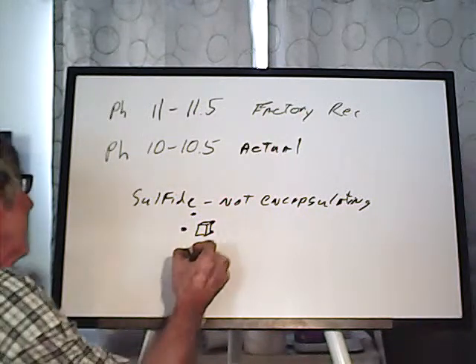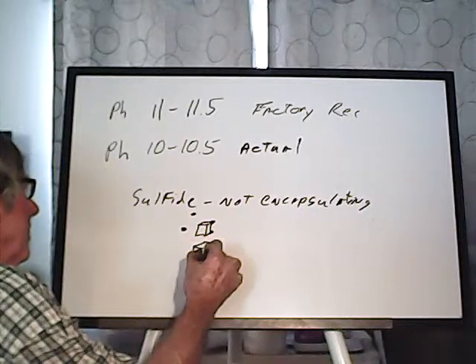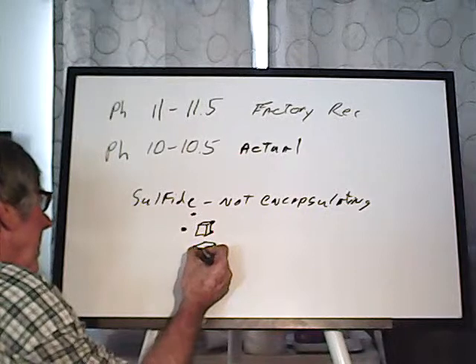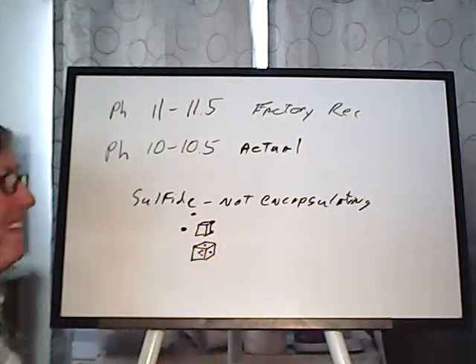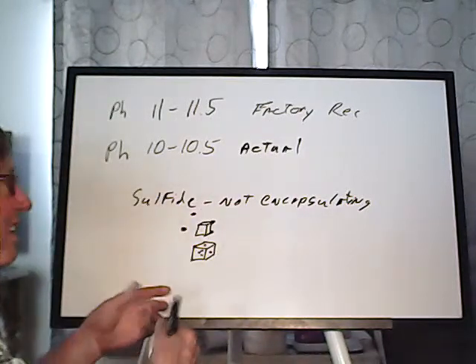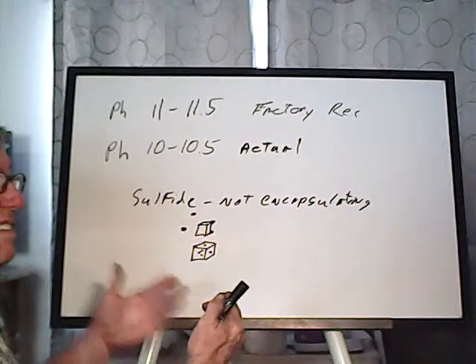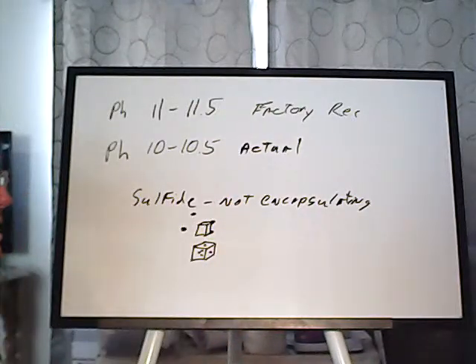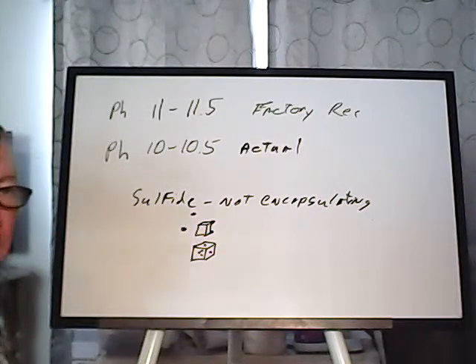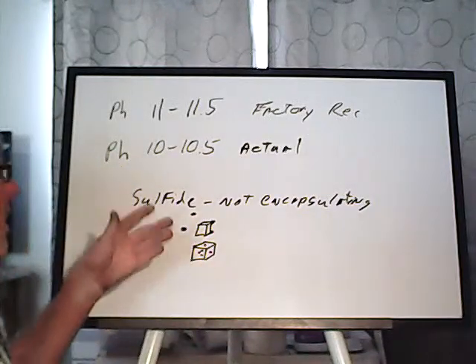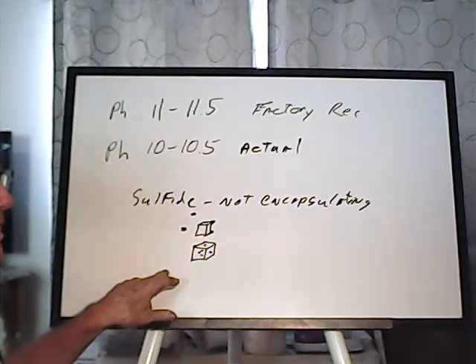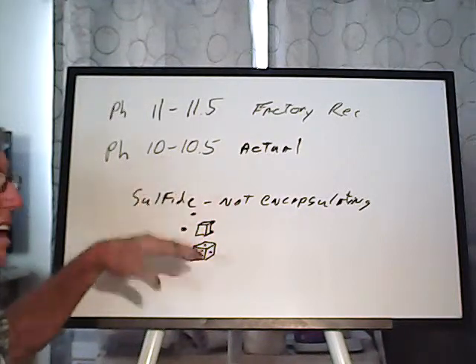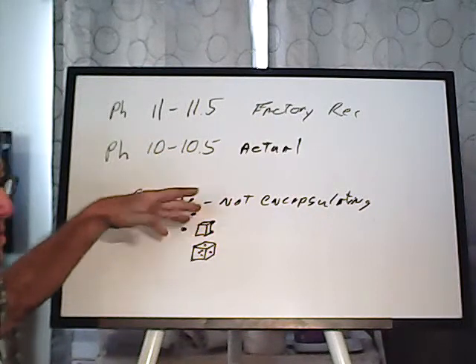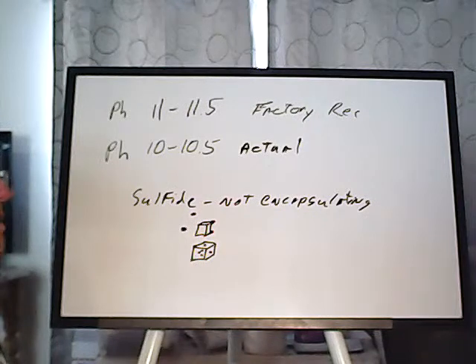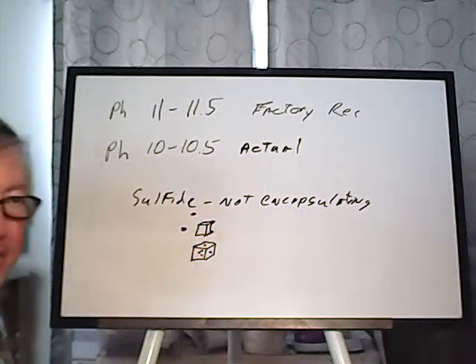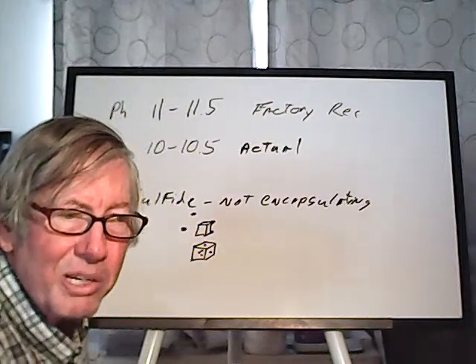However, in many cases, when you have sulfides, the gold is inside the sulfides. It's actually in them. Which means until you crush it fine enough to expose it, or oxidize it enough to make it porous where the solution can get through it, you're not even going to get the solution to the gold. You're not getting contact. And so that's why it could go either way on this. It's undesirable either way, but one is undesirable, the other is virtually impossible. And so that's where you wind up oxidizing the sulfide ores. Burning them off. I presume that answered your question, BR.